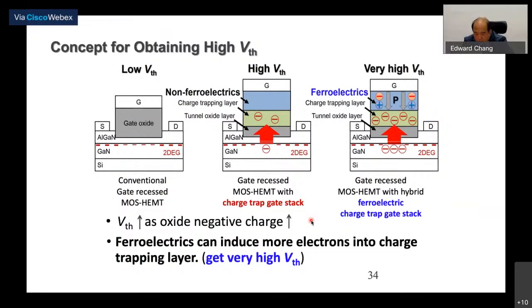Here we propose one approach. We use a ferroelectric. The idea is to use the ferroelectric to create an internal electric field which opposes the electric field you apply. In that way, when you apply a positive voltage to turn it on, the ferroelectric voltage works against it, so you have to apply an even higher voltage to turn it on. In that way, you increase your VTH. But the key point here is you have to have a gate stack which can generate a charge trapping layer, which will turn your ferroelectric in the right direction.